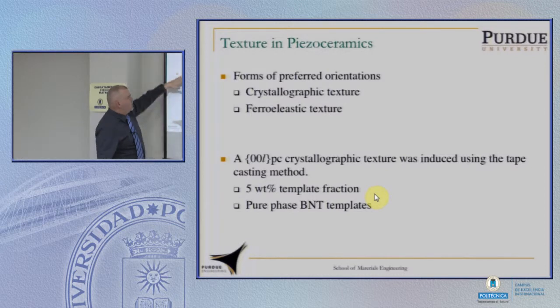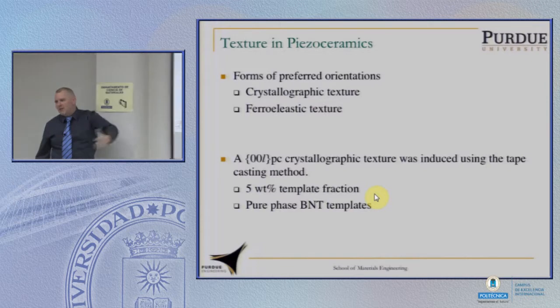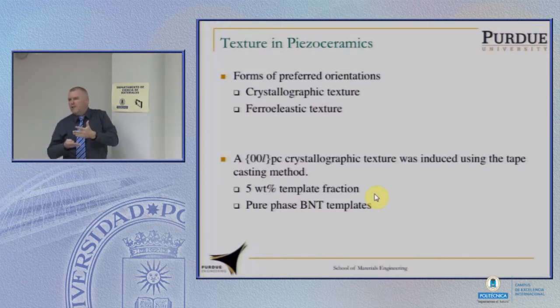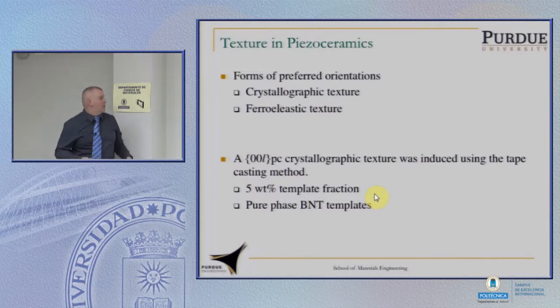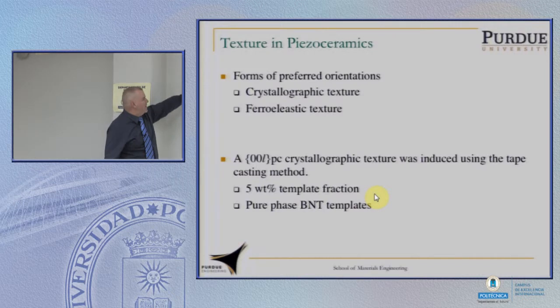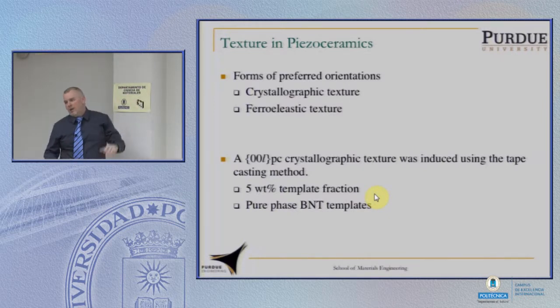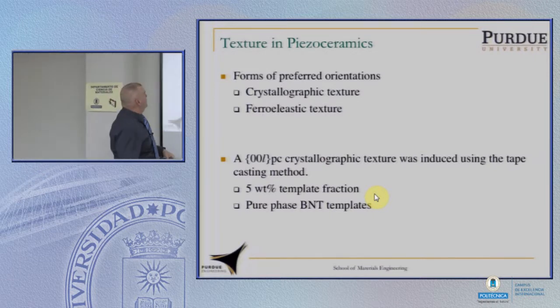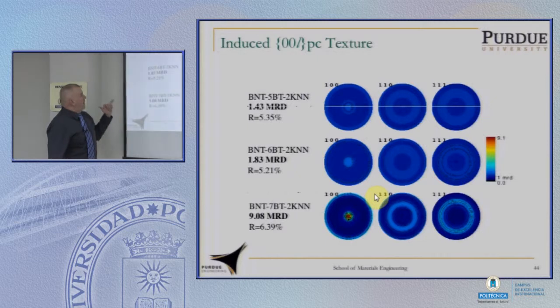Okay? So we use tape casting to produce these materials. Tape casting is essentially smearing the material out. If you put in platelets of crystals that have an extended shape to them, they tend to get oriented when you spread it out. And so Chris put in 5 weight percent of these materials that were essentially a BNT material. And so essentially we put in what we could treat as a seed to seed orientation in these materials. So these are the materials that Chris made.